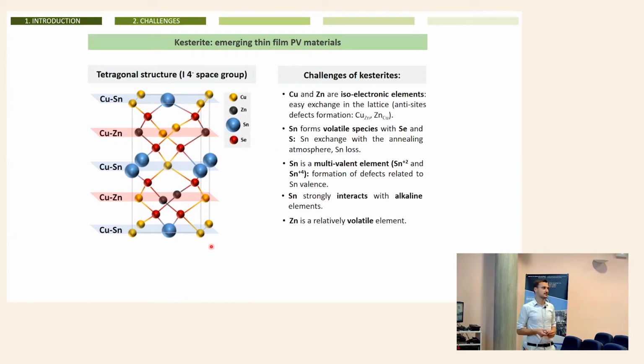In addition, we found some years ago that tin strongly interacts with alkaline elements, and I will show you that alkaline elements are really of vital importance in this technology. And this is an additional complication and very different from what happens with the CIGS. Finally, zinc is the least problematic of all of them, and sometimes can be volatile, but normally you don't have any problem with zinc, excepting this copper and zinc exchange.